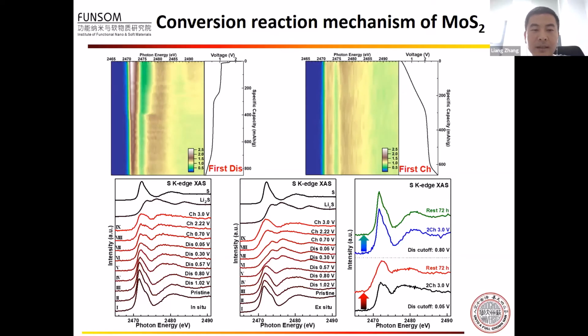So we further investigate the conversion reaction for the moly sulfide. Again, the upper are the in-situ results with the contour plot, and the bottom left is the in-situ spectra, and the right is the ex-situ results. From the ex-situ results we can clearly see the conversion from moly sulfide to lithium sulfide at the end of the discharge, because the spectral shape is very similar to that of lithium sulfide. During the following charge process, the structure of moly sulfide is not recovered, but the spectra look very similar to that of sulfur. This indicates the conversion reaction of the moly sulfide is not reversible.